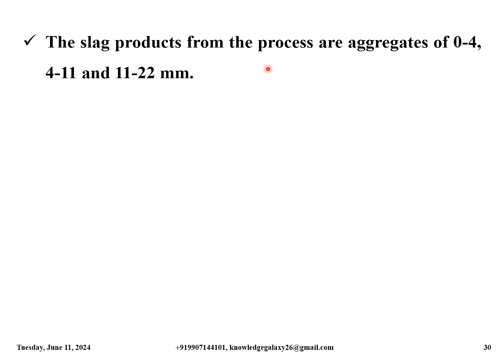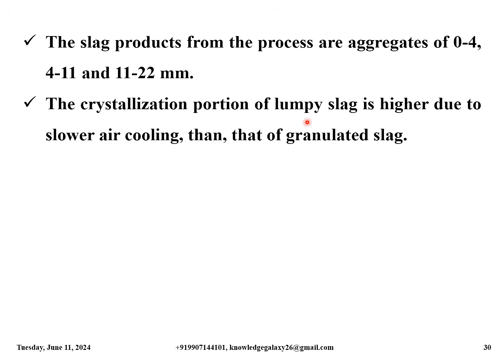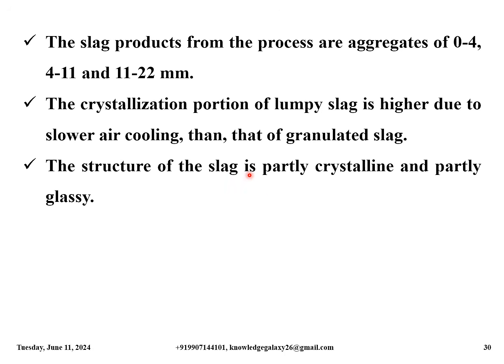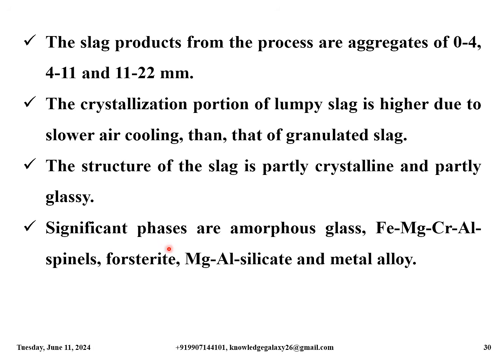The slag products from the process are aggregates of 0 to 4, 4 to 11 and 11 to 22 mm size fractions. The crystallization portion of lumpy slag is higher due to slower air cooling than that of granulated slag. The structure of the slag is partly crystalline and partly glassy. Significant phases are amorphous glass, iron, magnesium, chromium, aluminium spinels, forsterite, magnesium aluminum silicate and metal alloy.